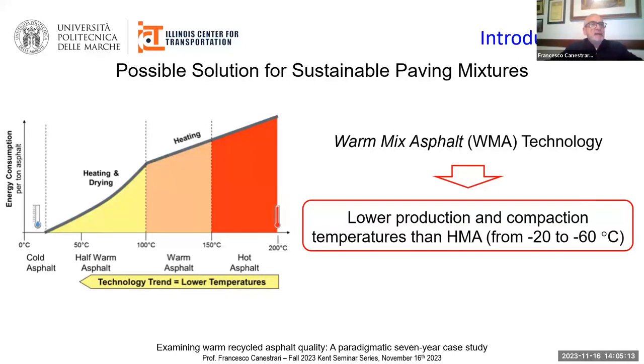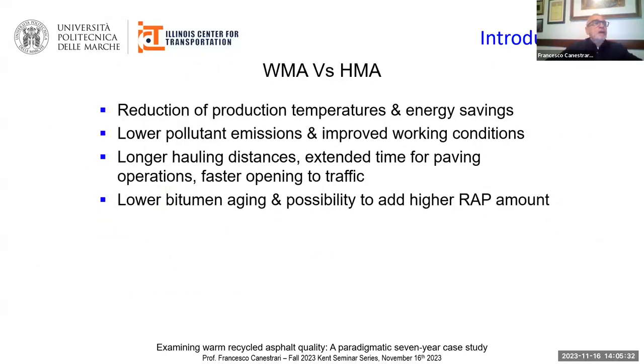Everybody knows that warm mix asphalt technology allows the production and compaction of asphalt mixtures at lower temperatures than conventional hot mix asphalt. The typical temperature reduction is in the range from minus 20 to minus 60 degrees C compared to hot mix asphalt. And therefore, the possible advantages of warm mix asphalt technology consist in reduction of production temperatures and energy savings, lower pollutant emissions and improved working conditions, longer hauling distances and extended working time for paving operations and faster opening to traffic. And from the point of view of the mixture, we could also have a lower binder aging and the possibility to add a higher amount of RAP.